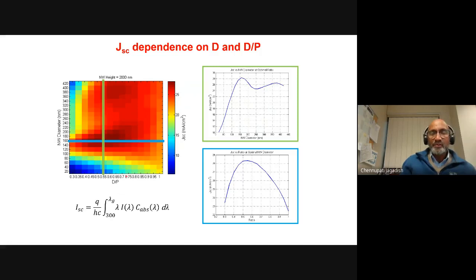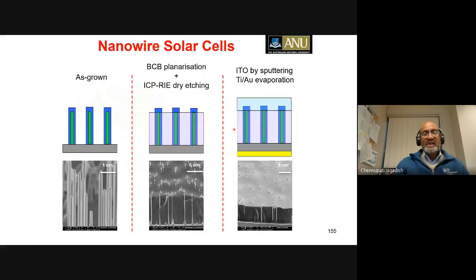Diameter to pitch ratio should be around 0.5 or 0.6 or so. You can see the short circuit current as a function of the diameter to pitch ratio, that's what we're indicating here. Based on these simulations, my students have grown these structures, the gallium arsenide, aluminum gallium arsenide structures, and this is the schematic of the actual sample. We fill this with